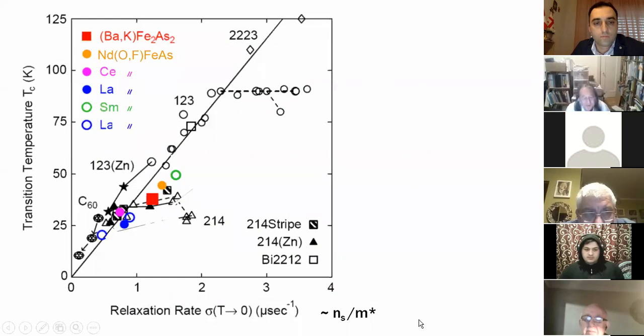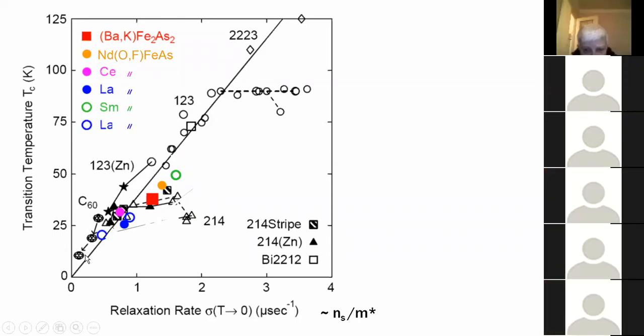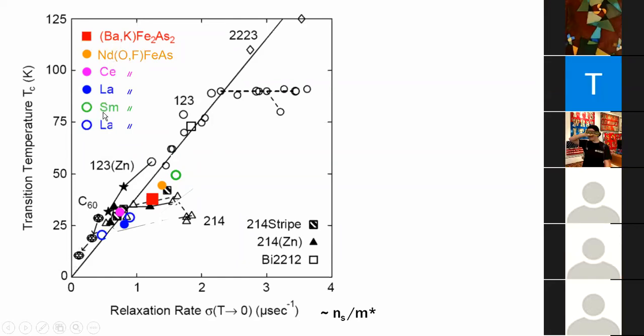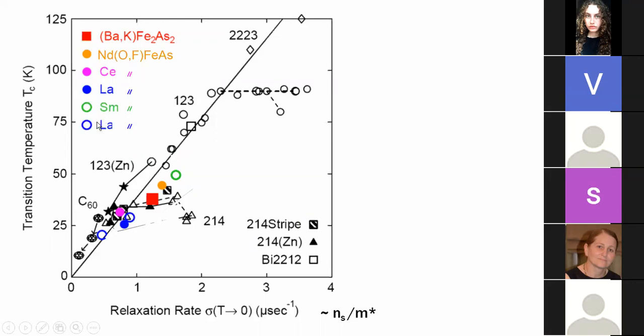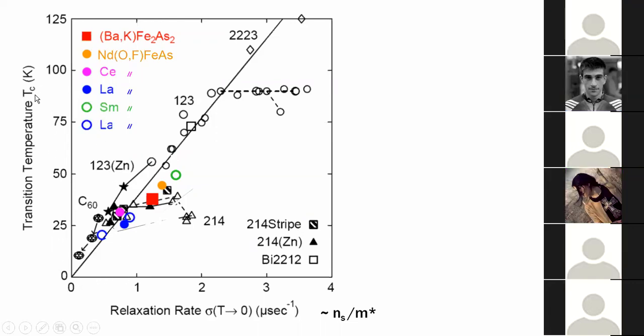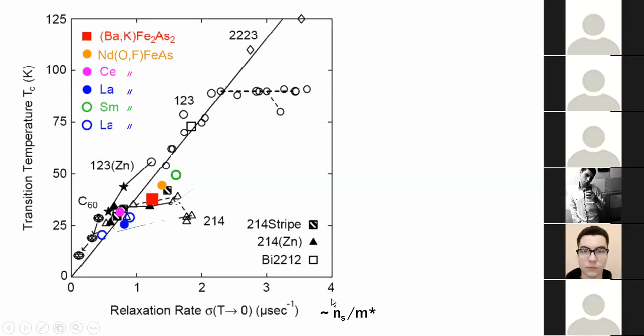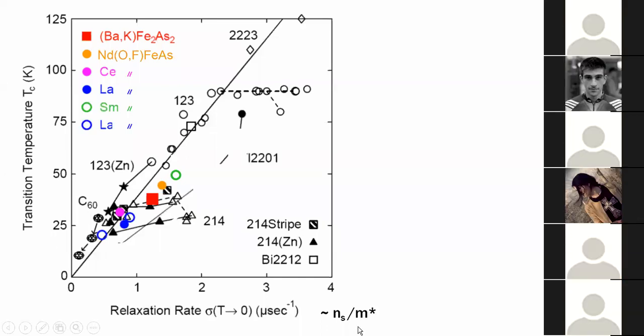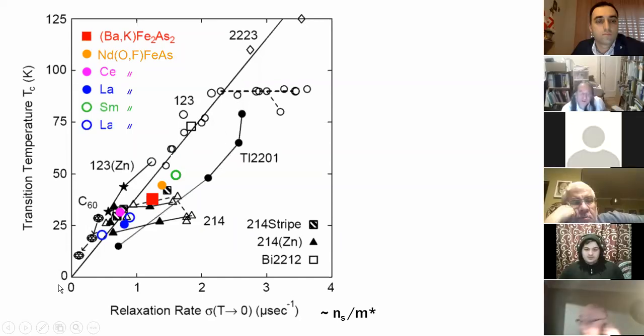Okay, then we continued because soon afterwards, many newer superconductors were discovered. Those buckyball, carbon-60 superconductors are one of them, but also slightly later, there are many materials like iron arsenide superconductors. They were discovered, and interestingly, if you do this experiment with muons, what you see is that this TC is always almost nearly linearly related to this superfluid density. There's something called the overdoped region, but the data is also more or less nearly linearly related. And so this is telling us that this feature is not only confined to one particular system, but more generally, universally taking place in many different new types of superconductors.